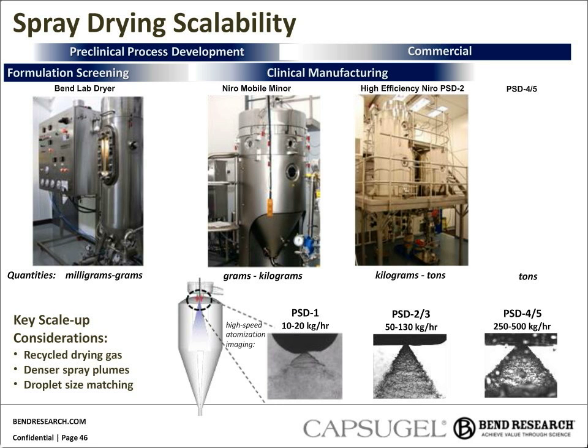But the second aspect to think about for matching drying rate or thermodynamics is the density of the spray drying plume, or the droplet density of the spray drying plume, which increases proportional to the feed rate across scales. And there are just many more droplets in nearly the same key control volume size. And this increased droplet density can cause a resistance to efficient heat transfer from the drying gas into the plume and mass transfer of the solvent vapor out of the plume at larger scales, effectively slowing down the droplet drying rate at larger scales. However, this effect can be easily predicted with scale factors and mitigated by increasing the drying temperatures at larger scales.